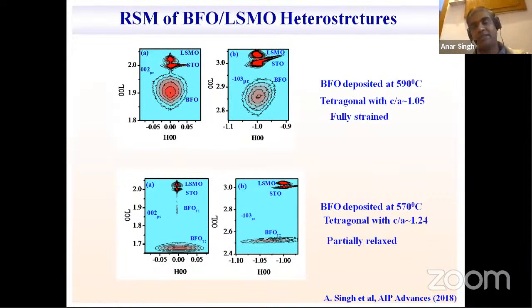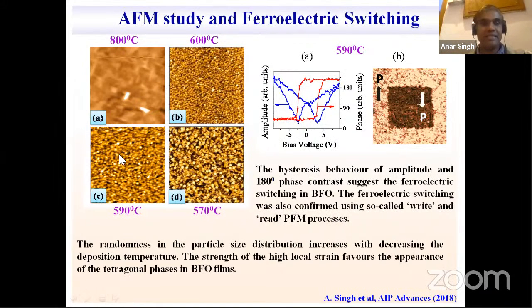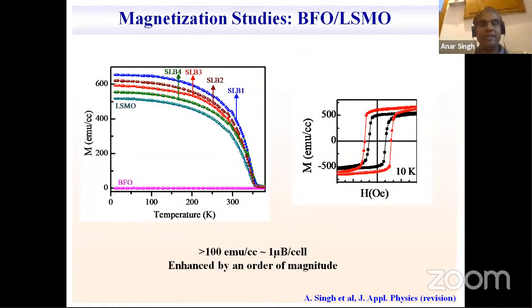to a tetragonal phase with a very large C/A ratio. So by changing the deposition condition, we can transform the monoclinic phase of bismuth ferrite to a tetragonal phase, which has a very strong polarization. And from AFM studies, we can see that the growth model has changed if we reduce the deposition temperature, and there is a kind of island growth, and a local strain is introduced because of this change in growth model, and this strain is basically responsible for the structural phase transition.